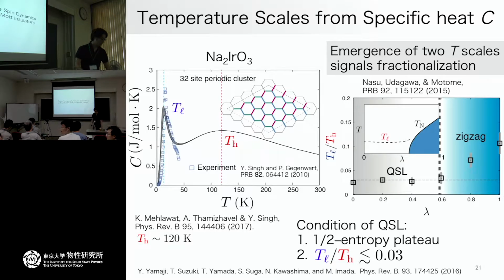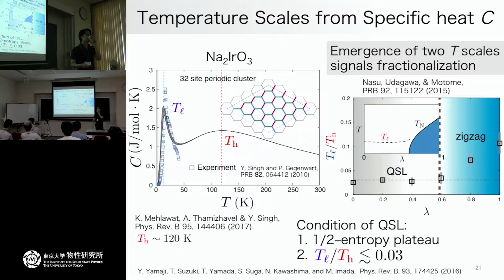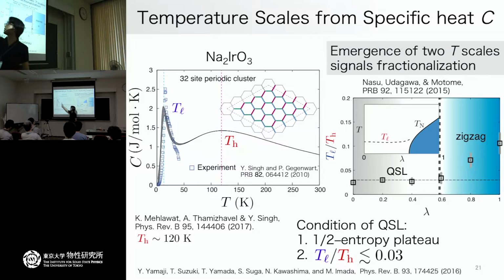Can I ask a question? Okay, please. The peak of specific heat at low temperature in the ordered phase, is it just the phase transition? It's a good question. It's a really difficult point, because if you calculate heat capacity at the Kitaev limit, we still have this kind of peak structure. So there is no clear connection between this low temperature peak and the ordered state. However, if we go inside this phase, then this low temperature peak signals the development of the long-range spin-spin correlation, which is also found in our simulation. In this phase, this temperature is a crossover temperature from the uncorrelated spins into the cooperative paramagnetic states.